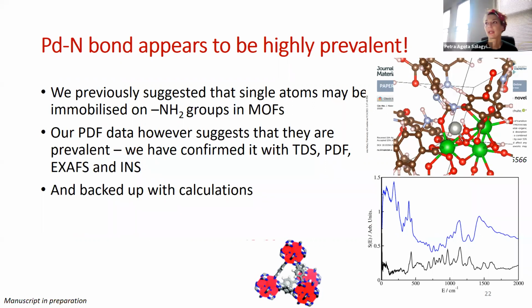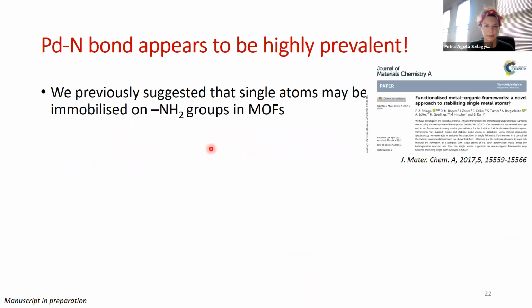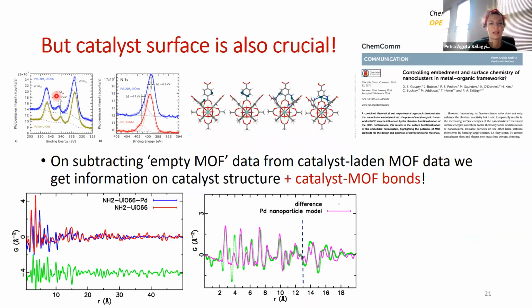Yeah, so it's positively charged, but according to the XPS at least, it's not a full charge or oxidation number change. In the amino one, I think I didn't put it up here. Yeah, so here we had a 0.7 electron volt difference. And I think an oxidation state change for palladium would come to about 1 or something like that. So it's oxidized, but it's not fully oxidized.